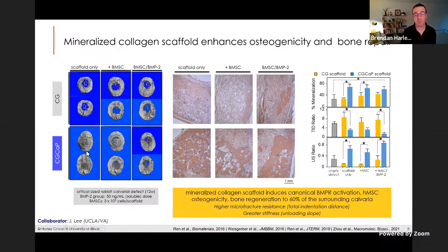And so the fact that we can take stem cells, put them in our material and have the material itself drive the process we want means that in a matter of weeks, we can regenerate bone that on its own would never grow back. And in fact, within a couple of months, we can get back about 60% of the native bone that was there before the injury. And so that's a massive amount of new bone that's growing. So this is one of our materials that we're thinking about going into clinical trials for.